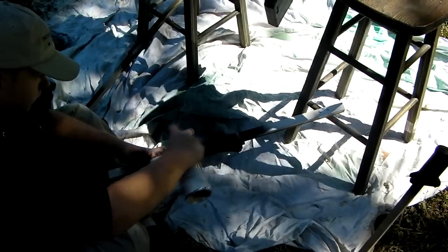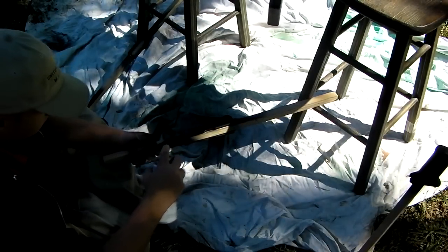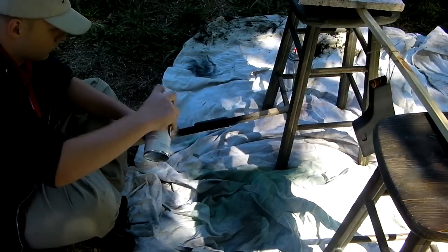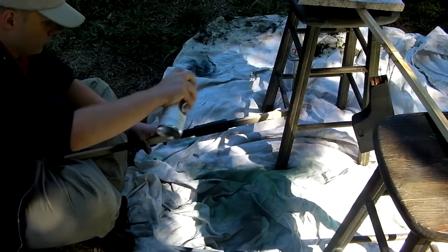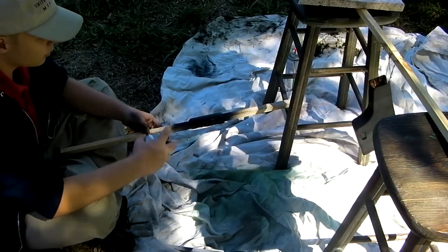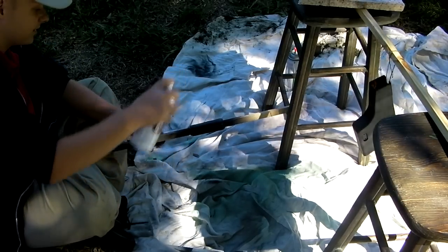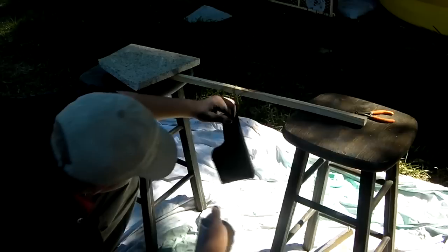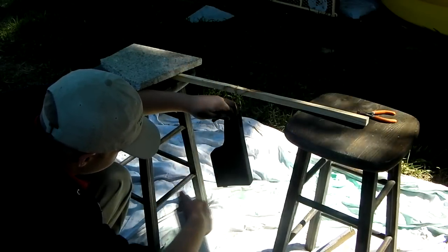The reason you want to be really careful with the clear coat is you can't put too much on there or it'll get sticky. You may think it's just going to dry and then it won't be sticky anymore, but no. I painted a pistol — just a really crappy plastic pistol — to test what it would look like, and it's still sticky. I spray painted it about three months ago and it's still sticky. You want to be really careful. Too much is sticky and shiny, and too little it's going to scratch off so there's no real point to having it on there.